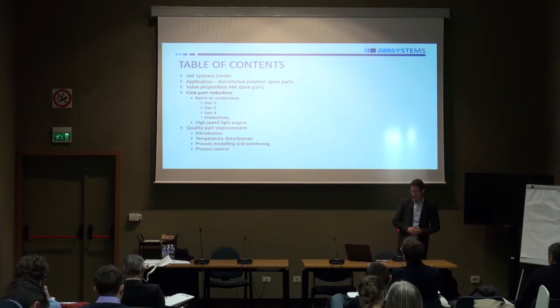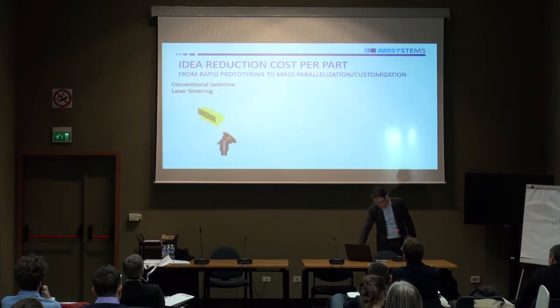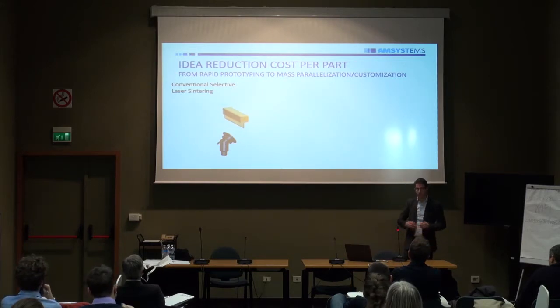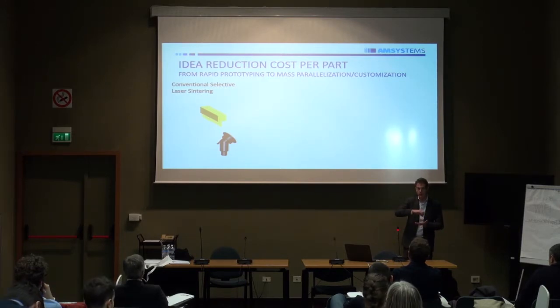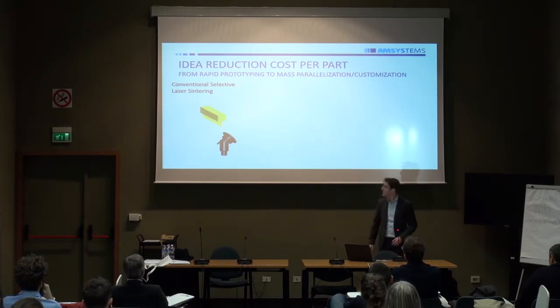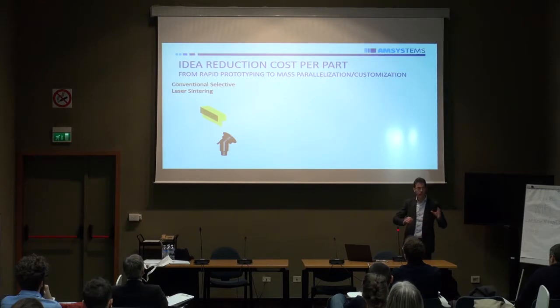To go to our proposition to reduce this cost per part. So what is the idea? If I go to selective laser sintering, the steps are coating a layer of polymer powder, it's typically PA12, but it can also be PA6. Then preheat it, and then selectively sinter the powder particles together, and then go to the next layer, as you saw with the animation. But typically these 3 steps are done in series: recoating, preheating, sintering.